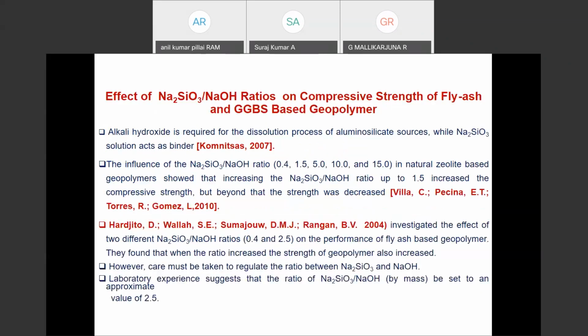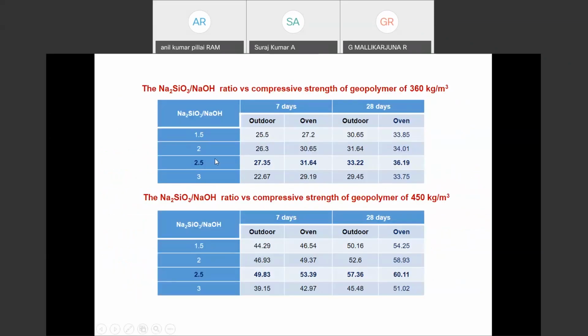Next, before going to further investigation, we considered the sodium silicate and sodium hydroxide ratio for the compressive strength. We considered sodium silicate to sodium hydroxide ratios from 1.5 to 2.5. Why? Because researchers identified these mixes and said that the concentration of sodium hydroxide is the maximum ratio. We are going to get the strength at 2.5, but here we get the maximum strength for 7 days and 28 days.